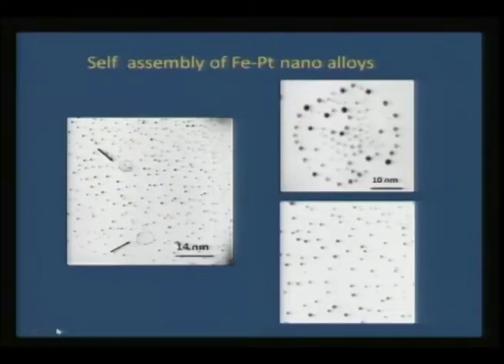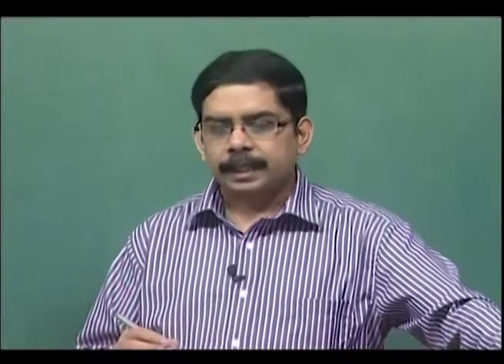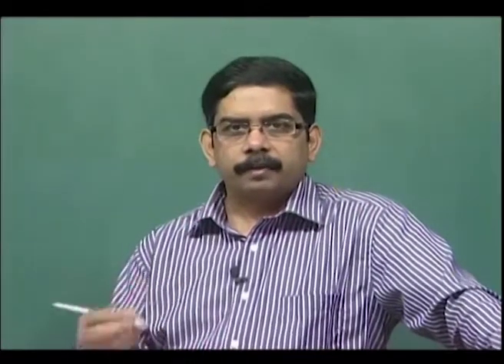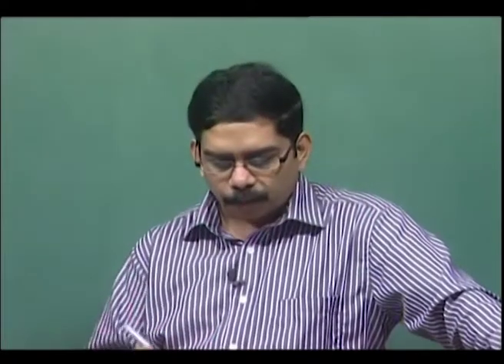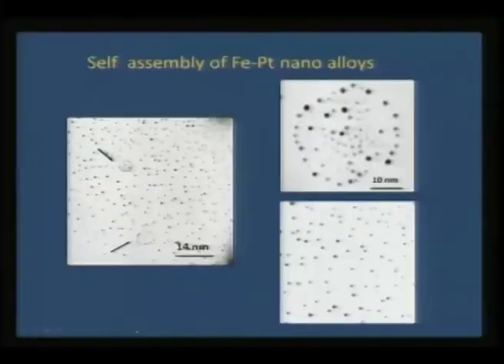How does the iron platinum alloy look? You can see from this TEM view graph that almost all the particles are monosized and of the order of 1 to 3 nanometers. This is very difficult because usually when we generate such nanophase alloys, you end up with agglomeration, and as a result, to stabilize these sort of alloys, usually we resort to some stabilizing agents or surfactants. But what we see here is that even without surfactants you can clearly isolate such alloys. And one fascinating feature is that throughout the TEM samples we keep observing this sort of self assembled pattern of iron platinum alloys, and they are held together in some sort of form,